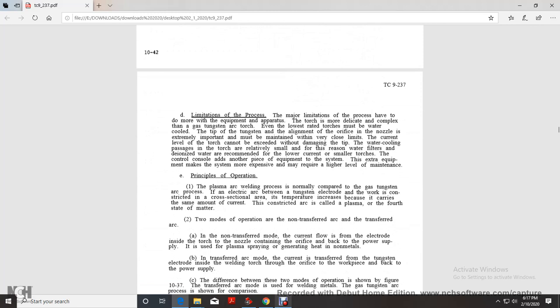Alright, the limitations of the process. The major limitations of the process have to do with the equipment and apparatus. The torch is more delicate and complex gas tungsten arc torch. Eventually, the lowest rated torches must be water cooled. The tip of the tungsten and the alignment of the orifice nozzle is extremely important, but must be maintained within very close limits.